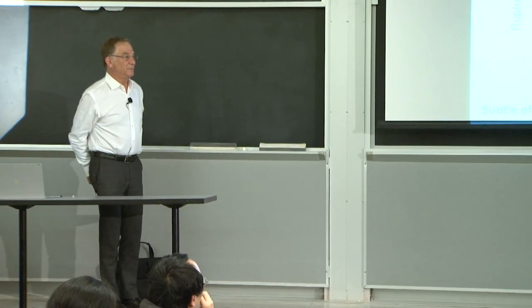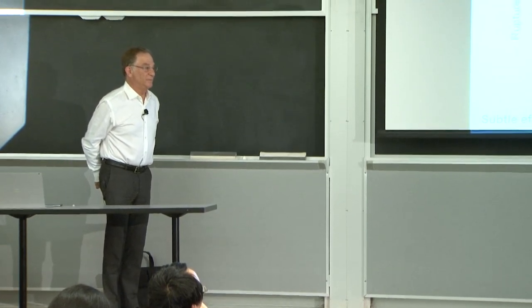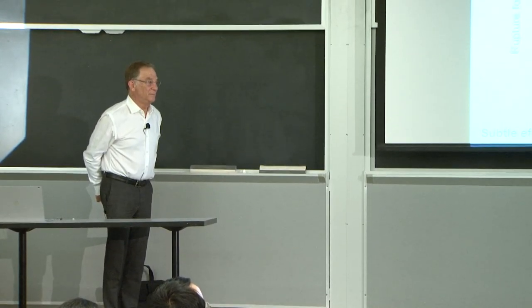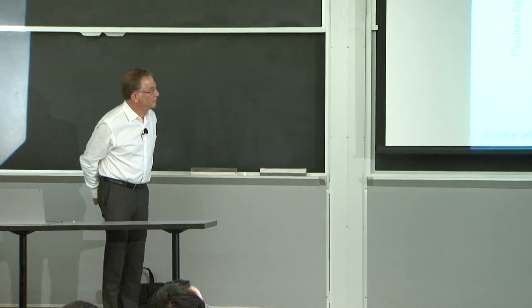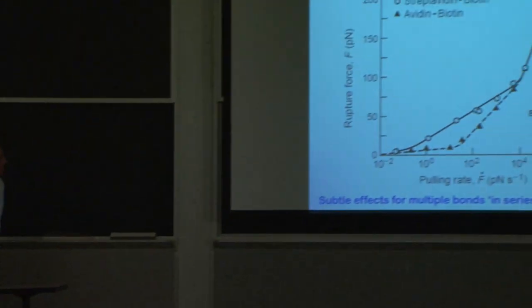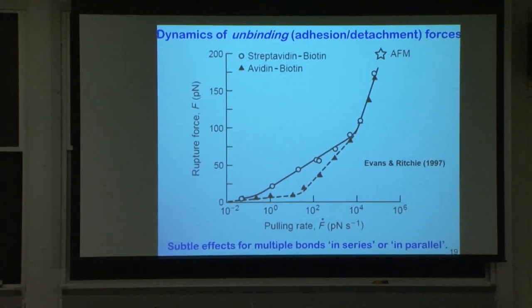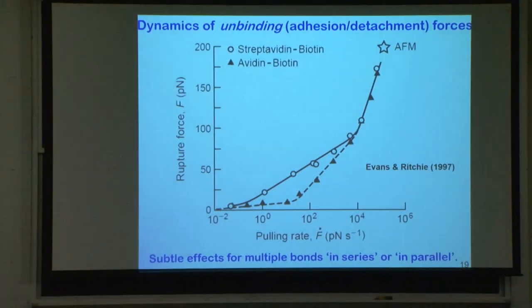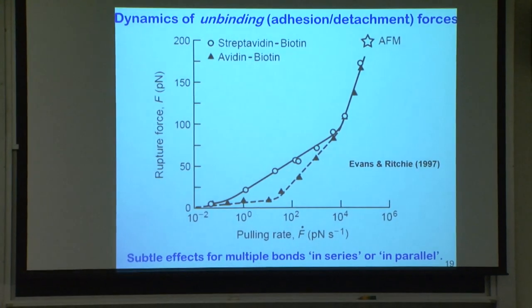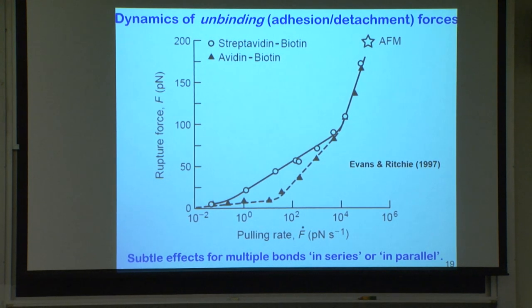Slide 19. So you show the rupture force as a function of the rate. And the data seem to suggest there are two regimes. At low rate the slope is relatively small, and then when you reach some critical rate, the force takes a much larger slope. It suggests some kind of crossover phenomenon, some kind of change in mechanism. Can you comment on that?